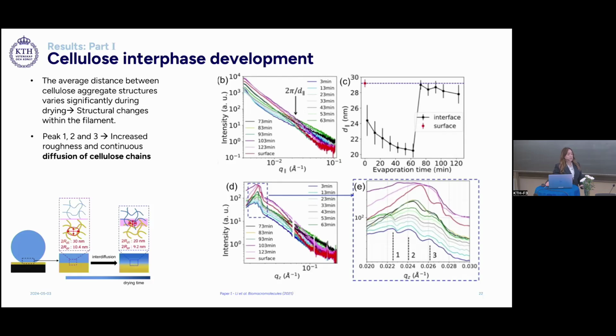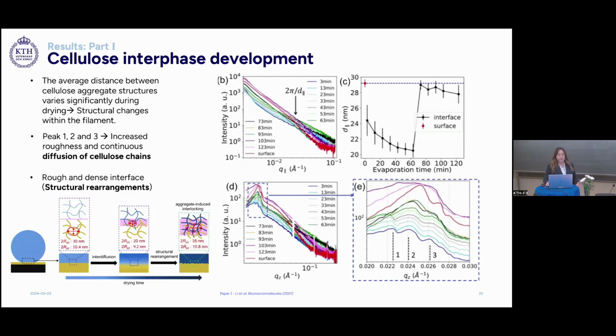And when the 2 surfaces are completely dried, we can see that the purple curves completely broaden and shift to a higher QZ. And this means that we have a newly formed, rougher and more dense interface, which is a result of structural rearrangement at the interfacial layer.